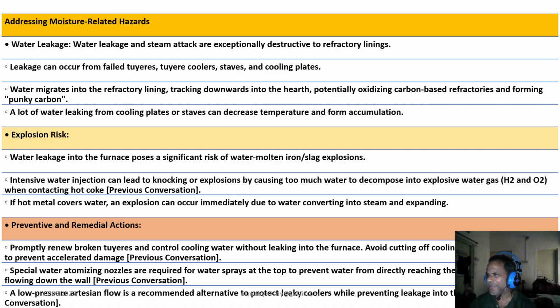Now, coming to our response, proactive and prompt actions are essential to manage these hazards. Firstly, we must promptly renew broken tuyeres and ensure cooling water is controlled without leaking into the furnace. It is crucial to avoid cutting off cooling water to leaky tuyeres, as this accelerates damage tremendously. Secondly, for water spray at the top of the furnace, special water atomizing nozzles are required. This prevents water from directly touching or reaching the burning surface or flowing down the wall, mitigating direct contact and potential hazards.